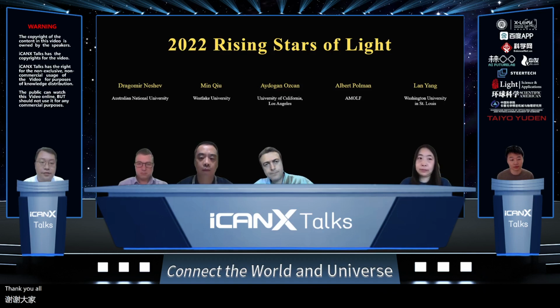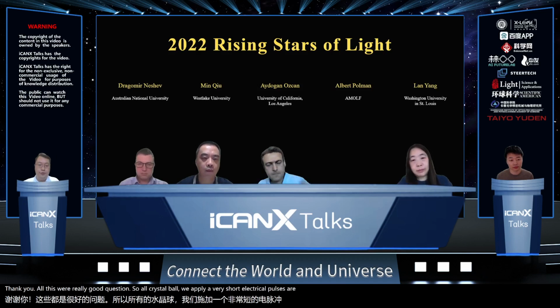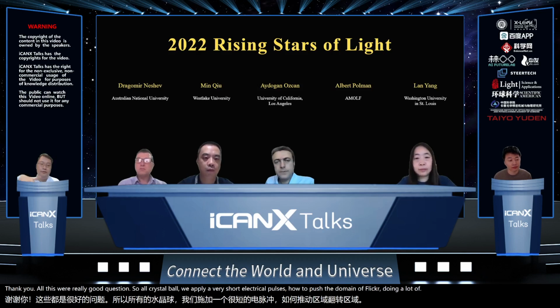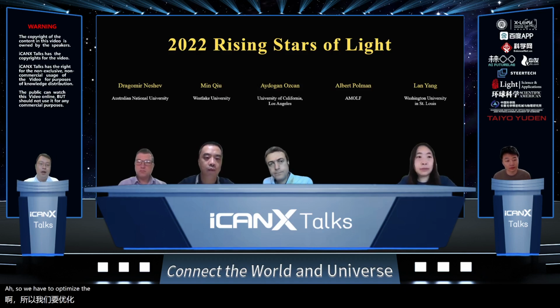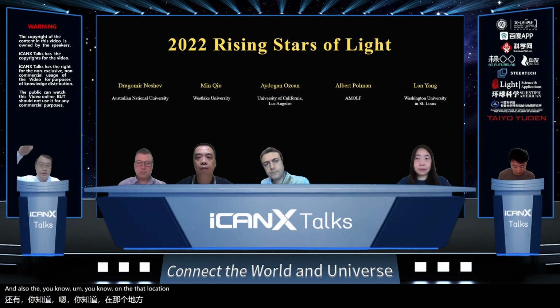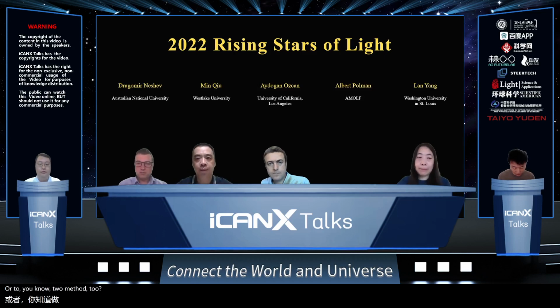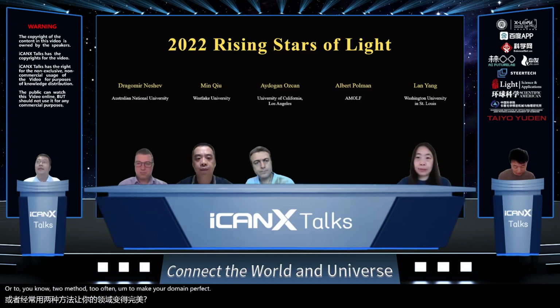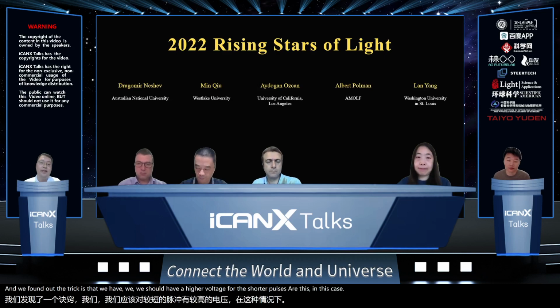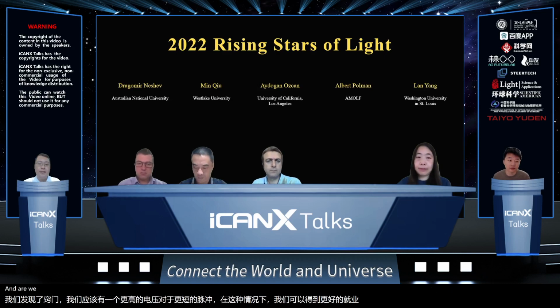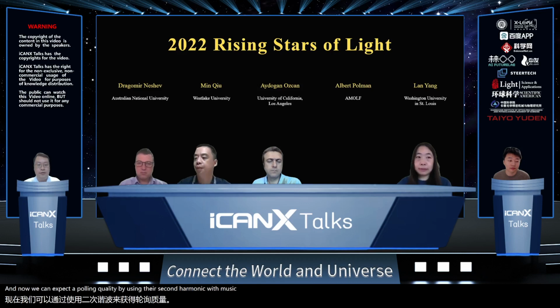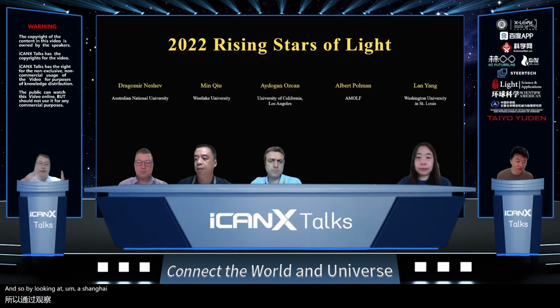Sure, thank you. This is a really great question. First of all, we apply very short electrical pulses to flip the domain along the waveguide. So we have to optimize the pulses, the length of the pulse, and also the voltage of each pulse to make the domain perfect. We found that the trick is to have a higher voltage but shorter pulses. In this case, we can get much better poling quality. And we inspect the poling quality by using a second harmonic microscope. By shining light and collecting just the second harmonic, we can look at the domain after the poling.